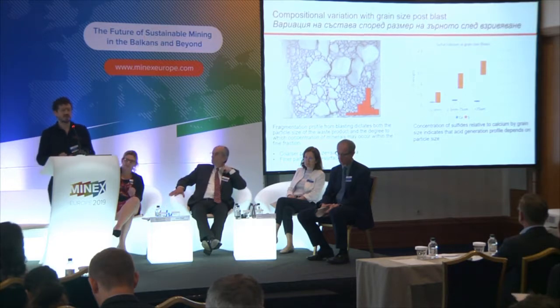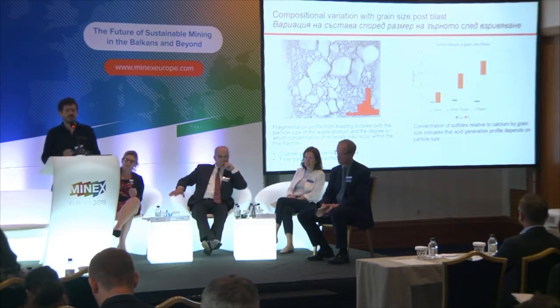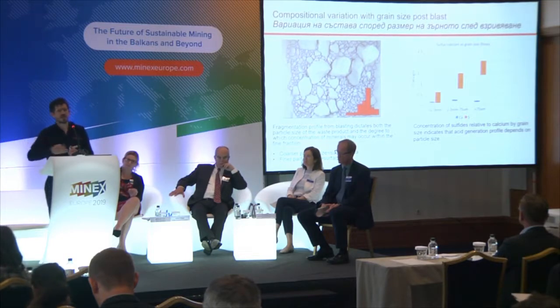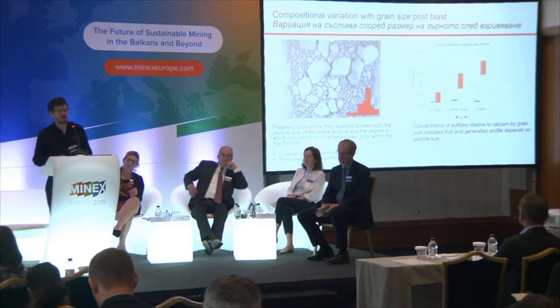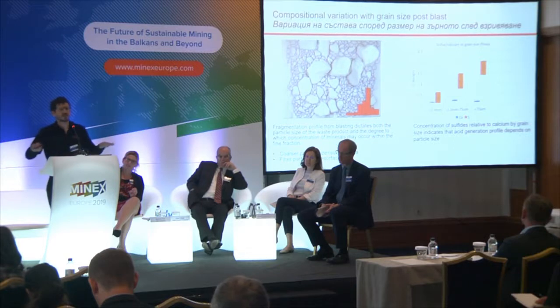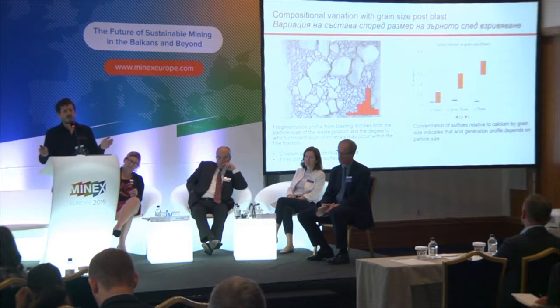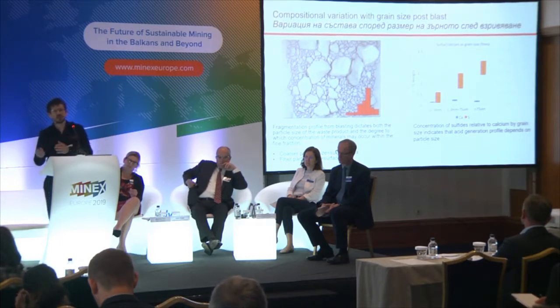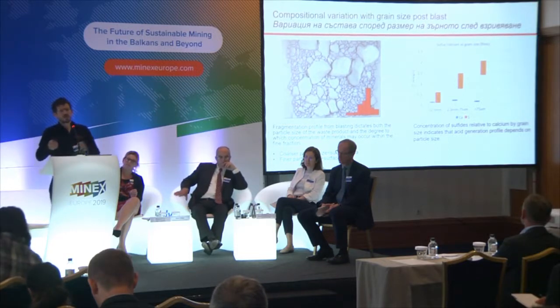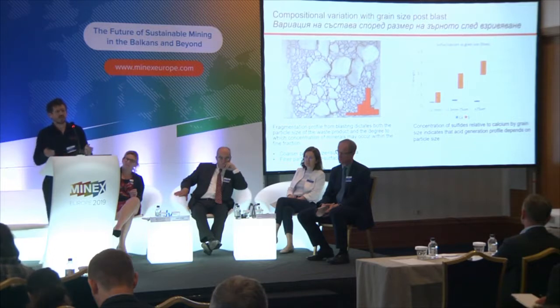So this is some data from the site, and you can clearly see, going through the grain size fractions, sulfide content is increasing in the fines. So you've got higher surface area, higher sulfide grade. Calcium, which is a neutralizing agent, is actually staying the same. So we're not seeing the same process between the calcium and the sulfur. So in acid mine drainage waste characteristics, a lot of the time it's buffering and acidity production is used to characterize it, but in the material that ratio can change depending on the fraction. So again, this fine fraction, which may be perceived to be low risk, could be much higher risk.